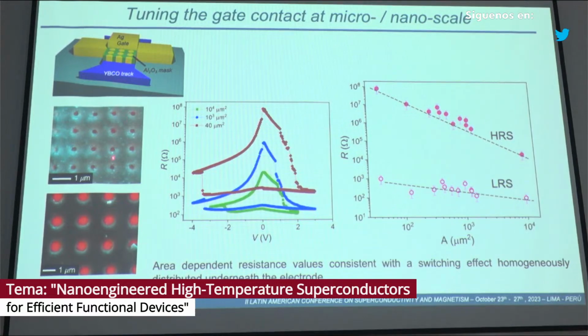And here, I show the properties of this system, which have also been found in different strongly correlated oxides and is what is called resistive switching, which means that you can change the resistance of the system by applying voltage pulses. In this graph here, I show the resistance versus voltage, and you see here that, for example, in this loop here, the red one, by applying a voltage pulse, we change the system to a very high resistance state, and then by applying a negative voltage, we come back to the low resistance state, which means that we have two different levels and also intermediate levels that can be modulated by applying pulses in the material.